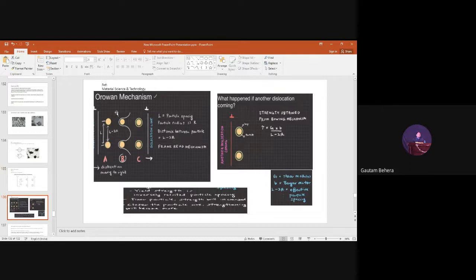The same thing is explained over here. This is a very beautiful image. You can again see this is a dislocation, and these are precipitate particles. The distance between the centers of the particles is L, and the distance between the particles is L minus 2R. The dislocation is bowing and forming a loop. And how does strength depend on this? You can see strength is equal to G times B divided by L minus 2R. So L minus 2R is the distance between the particles. If it is decreasing, strength is increasing.